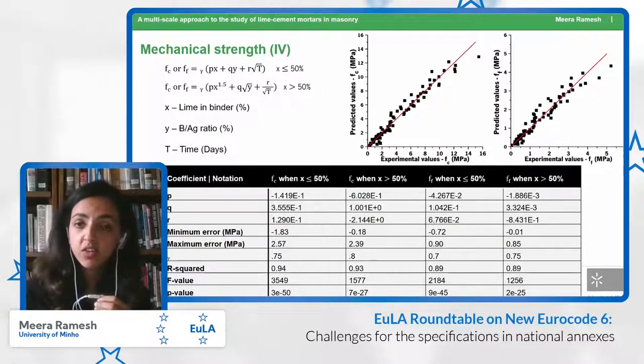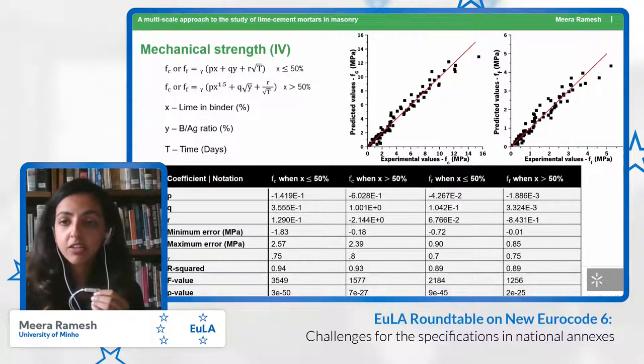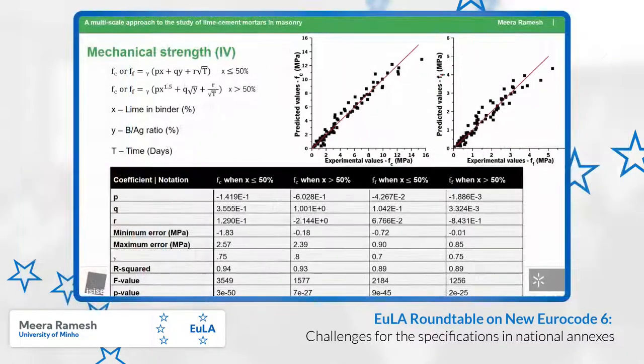Finally, we decided to take this one step further and see if we could express mechanical strength as a function of lime content, binder aggregate ratio, and time. Theoretically, what this implies is, as long as you know the composition of the mix you want, and the age at which you want to know the strength, you should be able to obtain it.